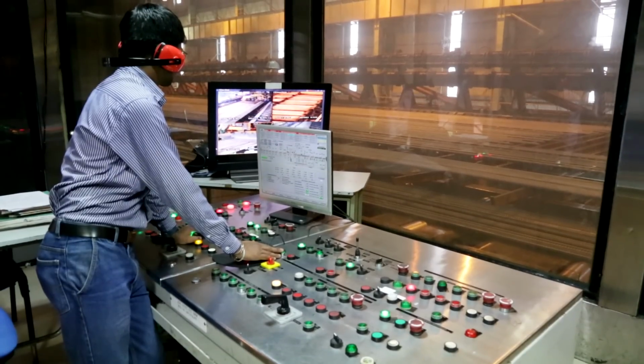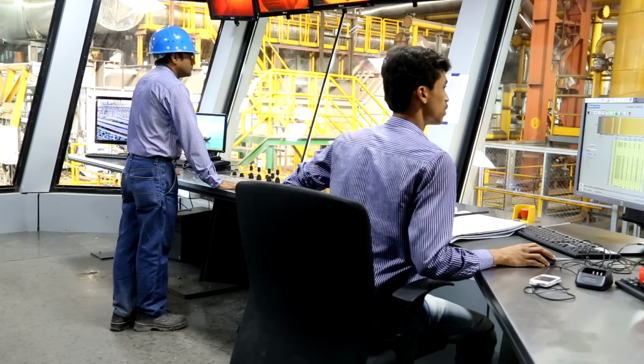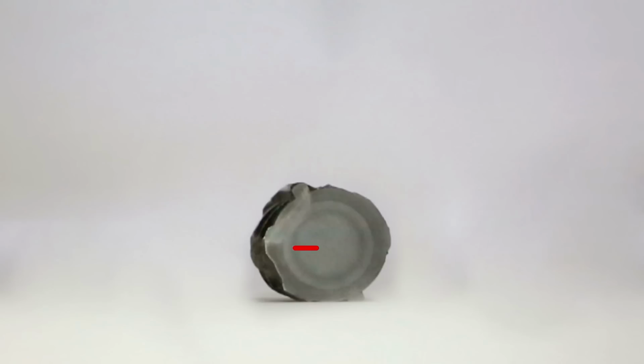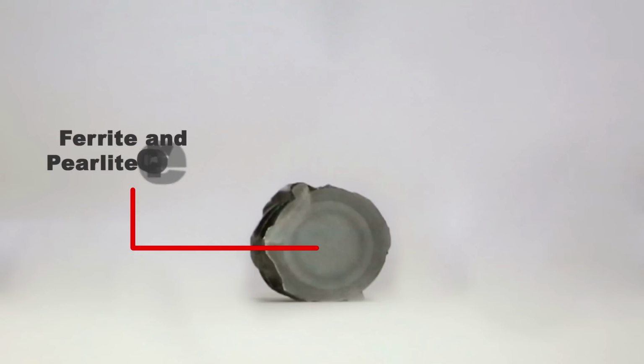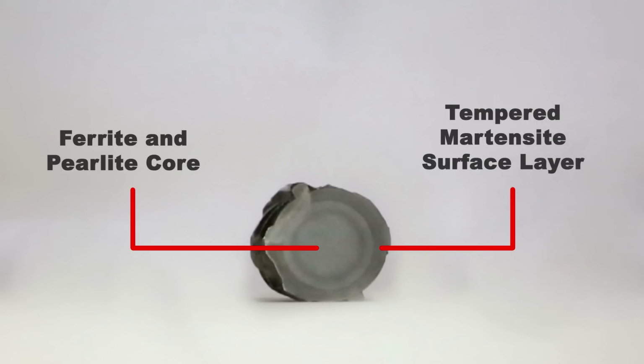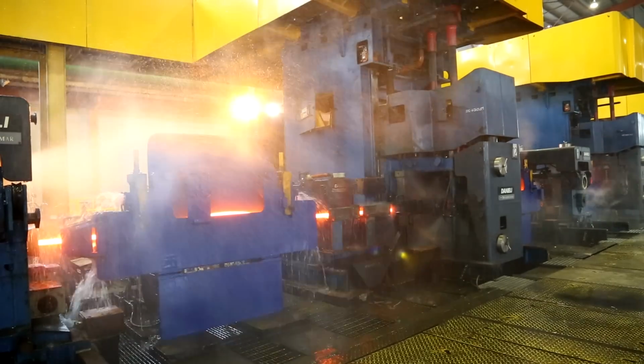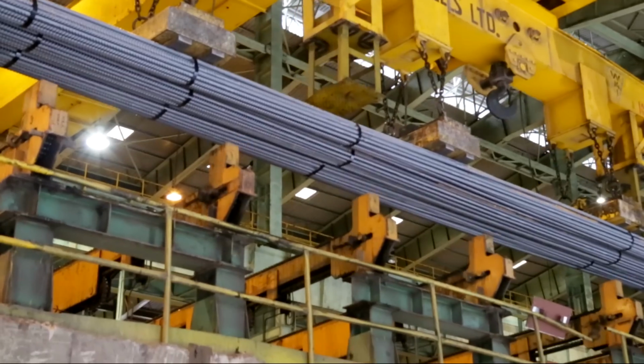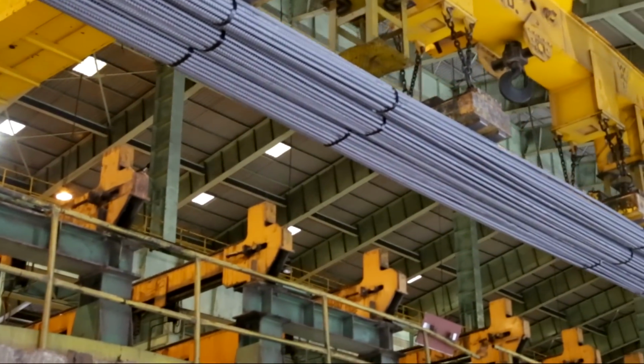This latest computer-controlled rapid quenching system with metallurgical rationale ensures a fine equiaxed ferrite pearlite microstructure at the core and hard and tempered martensite on the outer surface. As a result, the bar has a combination of superior strength and high ductility.